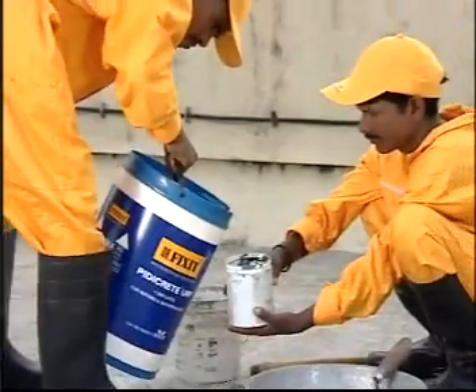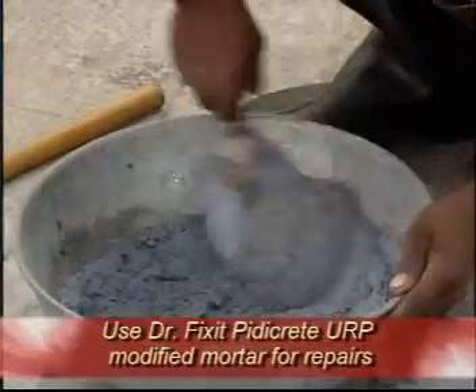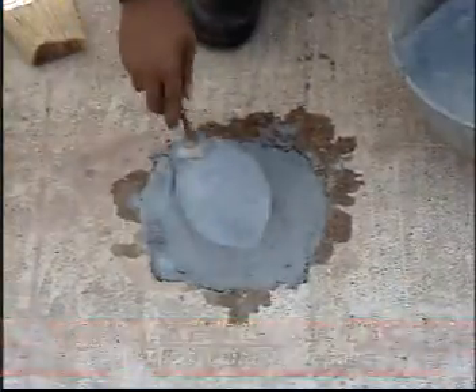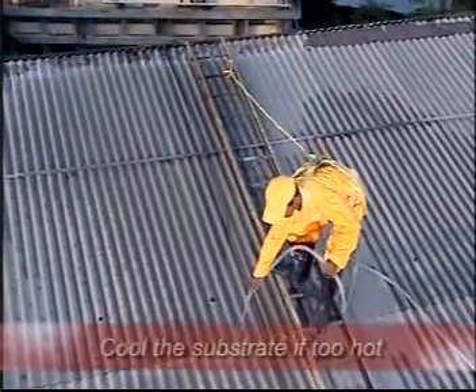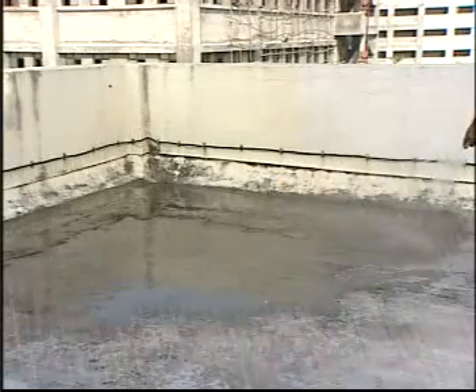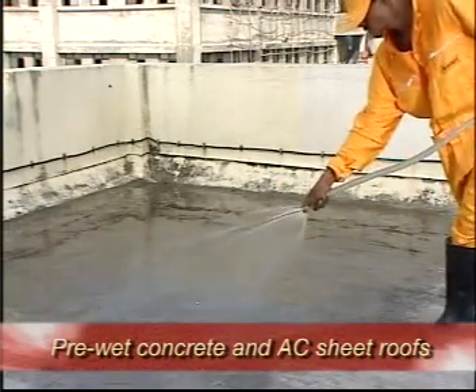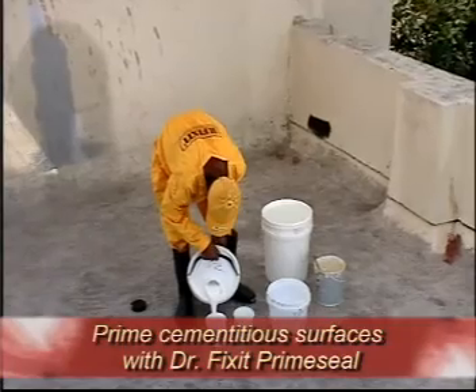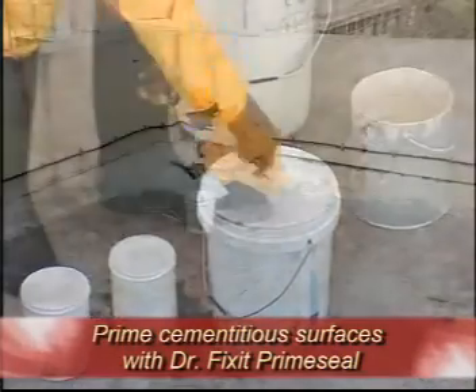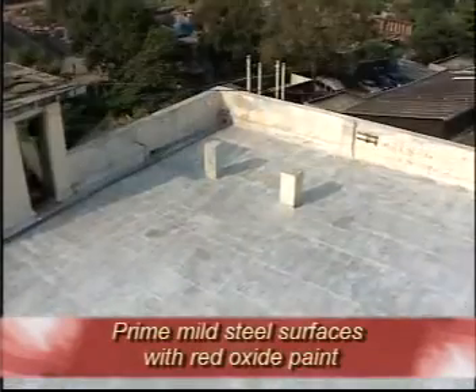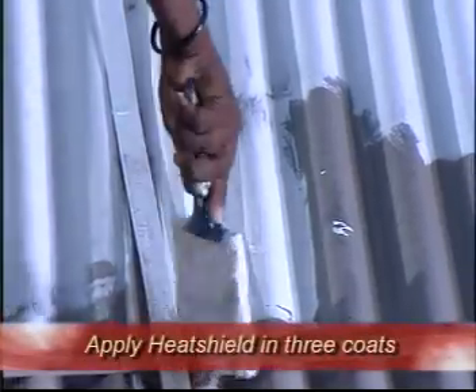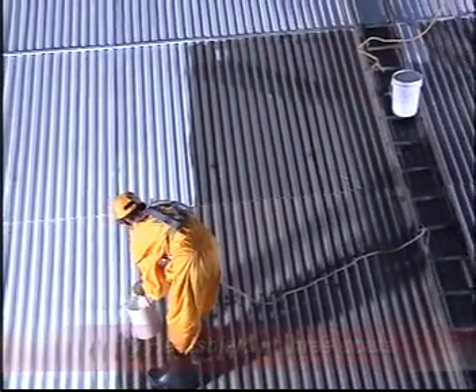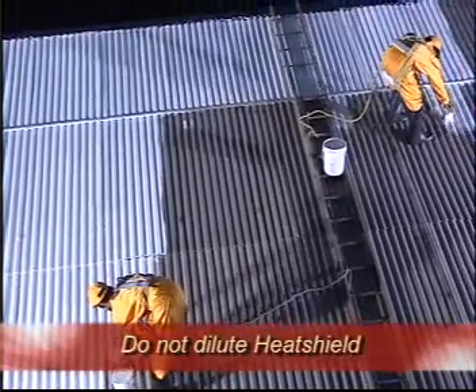To quickly summarize, first, make sure the surface is sound. Repair unsound cementitious surfaces with Dr. Fixit Pidicrete URP modified mortar. Second, clean the surface. Third, cool the surface if it's too hot. Fourth, cementitious surfaces should be pre-wetted. Fifth, prime the surfaces using Dr. Fixit Prime Seal for cementitious surfaces and red oxide paint for mild steel surfaces. Finally, apply Heat Shield in 3 coats with at least 2 to 3 hours between coats. Do not dilute Heat Shield.